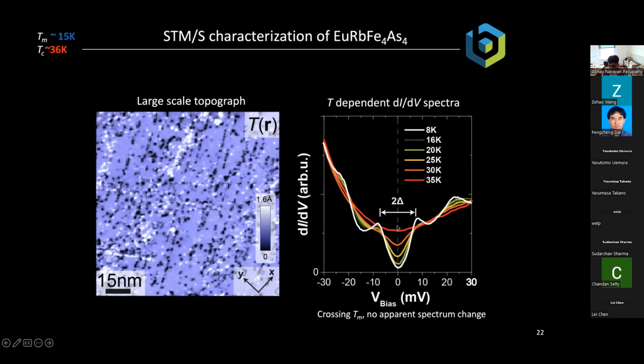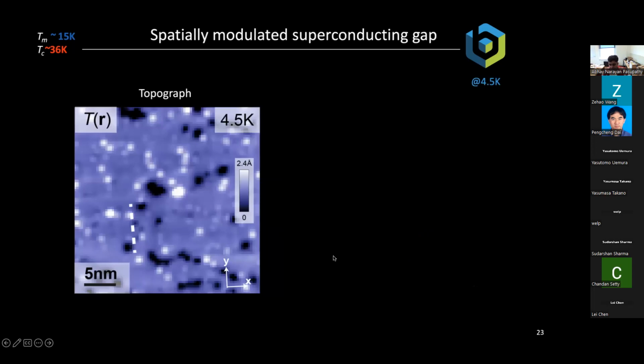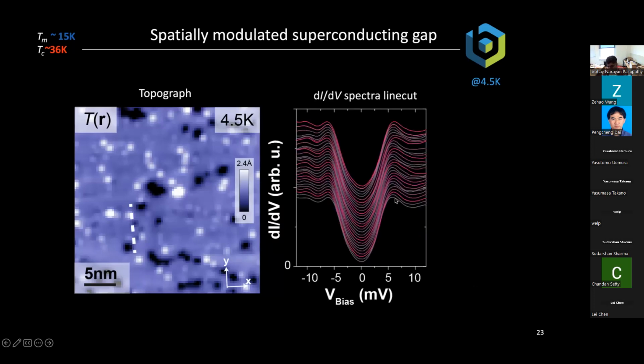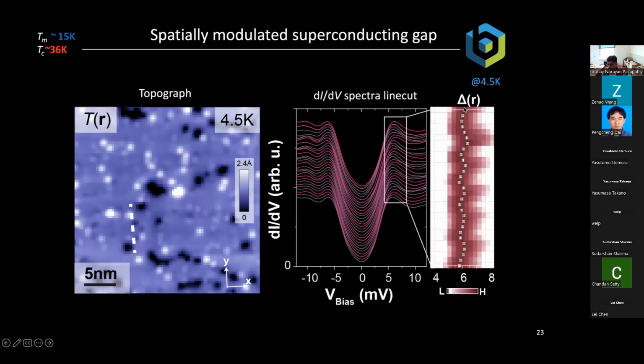Now, these measurements that I'm showing you right here are taken at one particular point on the sample. So I just park my tip over one particular atom and I take these measurements, and this is what one might get. And the interesting thing that we want to ask in this material is what happens as I take my STM tip and go from point to point and measure how this gap changes from point to point. And so what I show you here is a surface topograph. And if I go along this white line and I measure the superconducting gap at every point in space, then what you can see, and let me zoom into the edge of this superconducting gap, is you can see that this gap modulates in a nice fashion, somewhat sinusoidally, as you go across in space. And so this was really the interesting finding when he first stuck in this sample, is that the gap is not constant in space, but instead it shows a sinusoidal modulation as you walk across the sample.